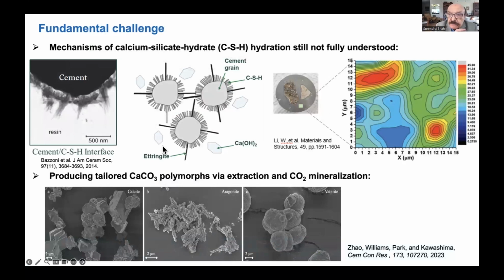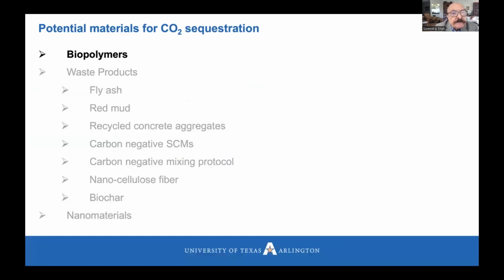Also important is controlling the morphology of calcium silicate hydrate. This is more complex because CSH, even at the nanoscale, is very heterogeneous. For example, here are shown nano indentation values using atomic force microscopy of calcium silicate hydrate. So the challenge is how to control the morphology of CSH and how to manipulate the coupling between hydration and calcium carbonate.